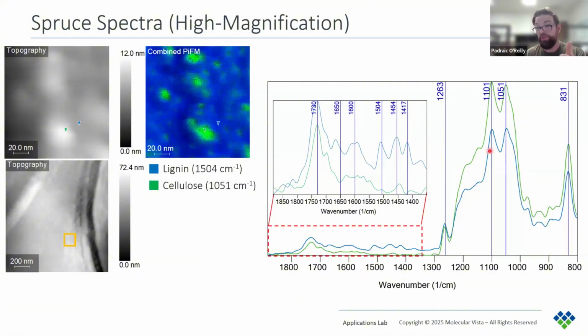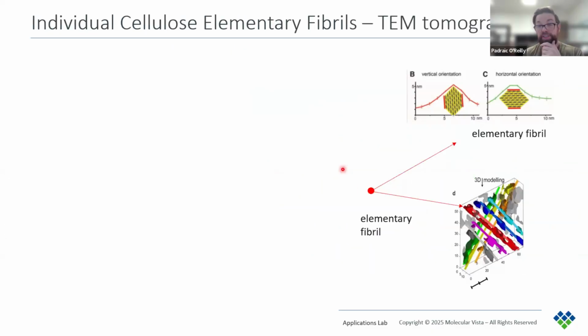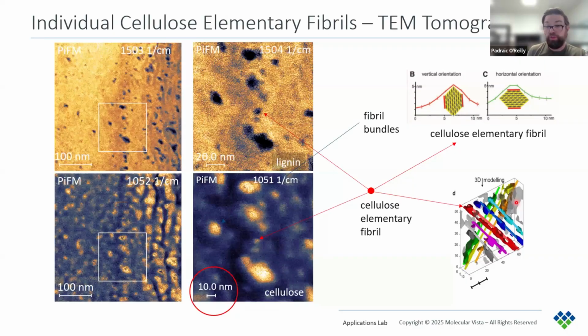And the spectra also confirmed this. So with the green area showing this strong broad peak centered around 1100, and the blue increasing below 1300, which is what we saw in the FTIR reference spectra. Now, the TEM tomography that they did indicates that there are these elementary fibrils running through this part of the cell. And the composition of these fibrils, as we just showed, are cellulose.